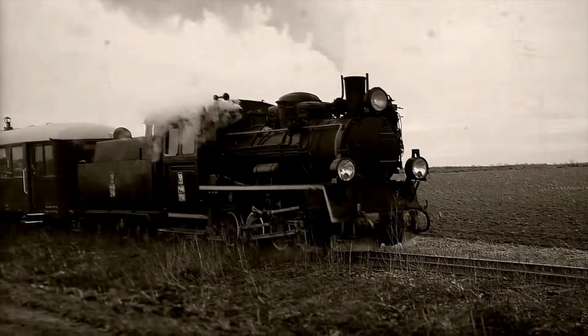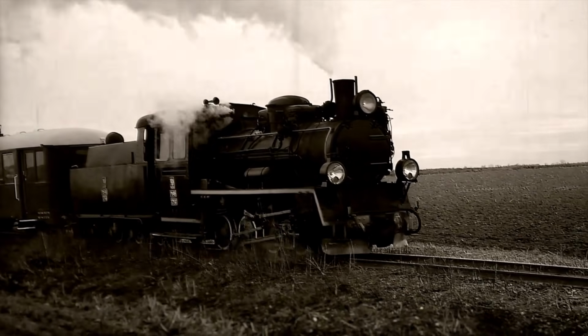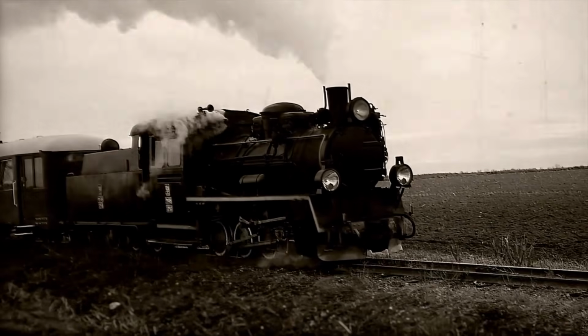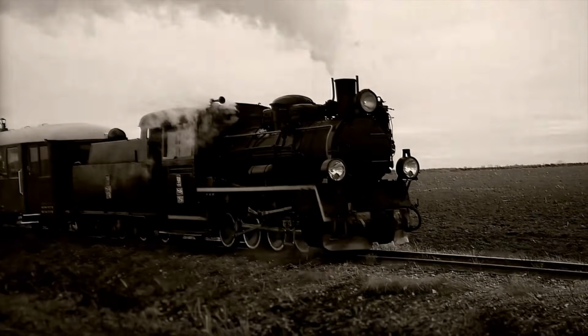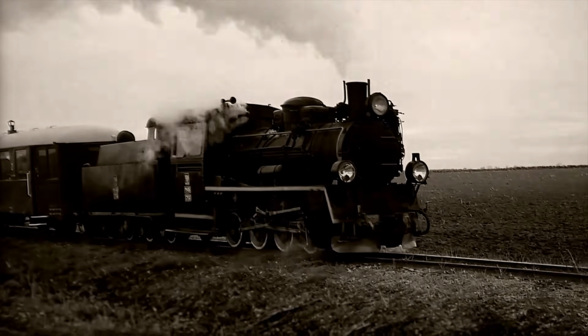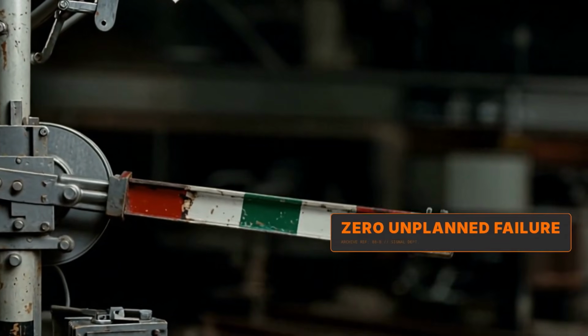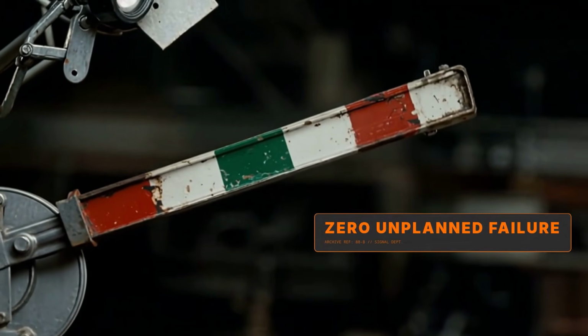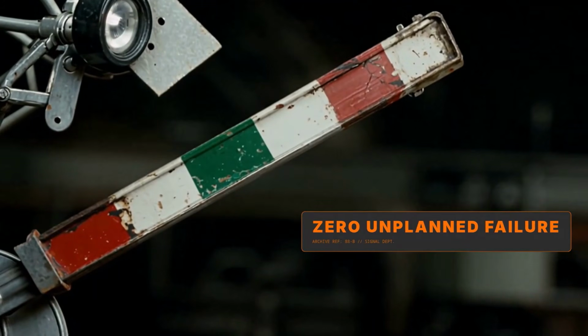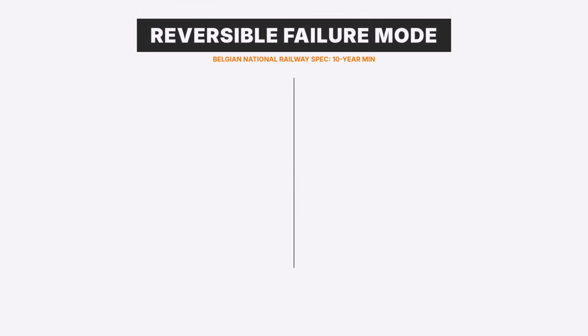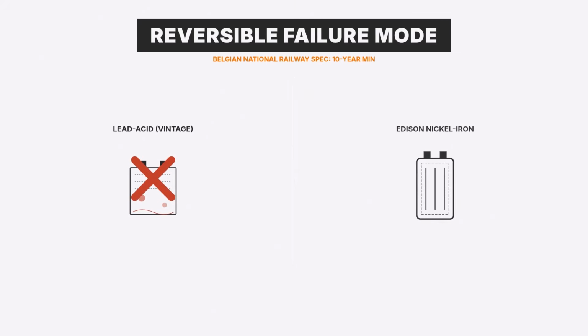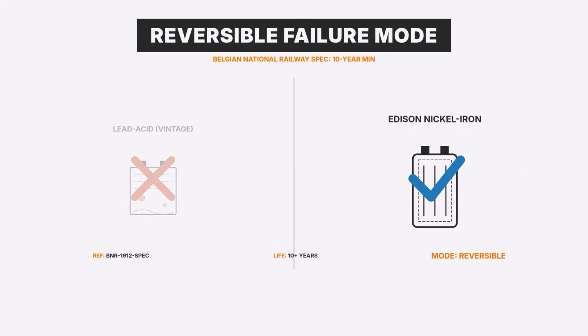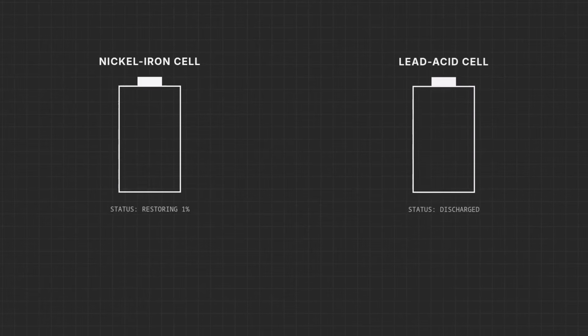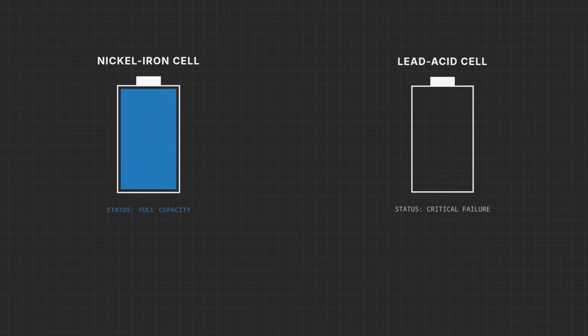By 1910, as European railway networks expanded their signal infrastructure across the continent, Belgian National Railway engineers specified the Edison nickel-iron cell for emergency power in signal systems that could accept no unplanned failure. Railway signal batteries were the most demanding application the period's electrical engineering community had yet identified; a signal battery that died stranded trains and killed people. The Belgian National Railway's specification required a minimum 10-year service life under continuous float charge with no electrode replacement. They chose the Edison cell not because it was fashionable, but because it was the only chemistry whose failure mode was documented as reversible. A discharged nickel-iron cell could be restored to full capacity. A failed lead-acid cell could not.